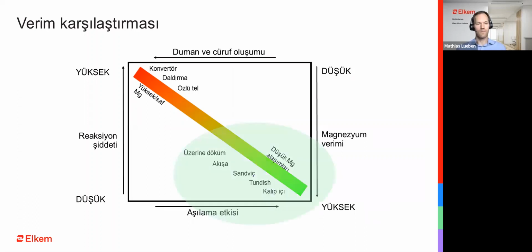Arif, please, one click. Thank you. Take a look at the green circle. Treatments with low magnesium containing alloys will result in a high magnesium recovery with proper inoculation effect. And the treatment will cause less fumes and slag formation. So at the end of the day, with a magnesium ferrosilicon treatment, you will achieve a high treatment efficiency, reduced fume and slag, a cleaner iron, superior metallurgy, low consumption of magnesium, reduced energy cost. You will improve your casting yield, and in the end, you will get lower reject rates.